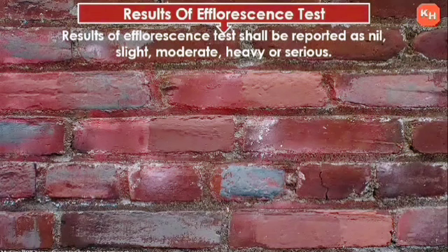Heavy. When there is a heavy deposit of salts covering 50% or more of the exposed area of the brick surface, but unaccompanied by powdering or flaking of the surface. Serious. When there is a heavy deposit of salt accompanied by powdering and or flaking.